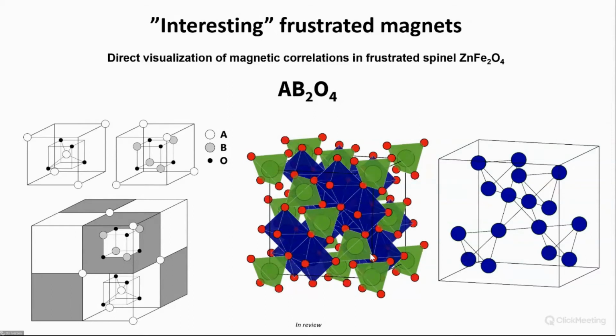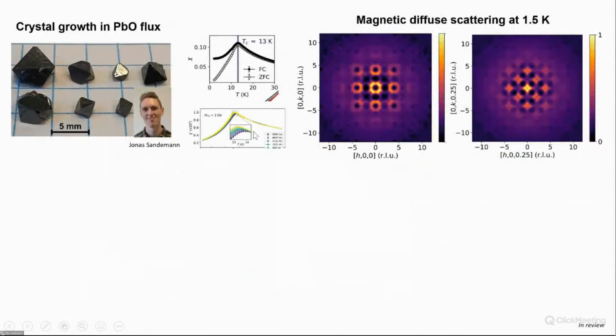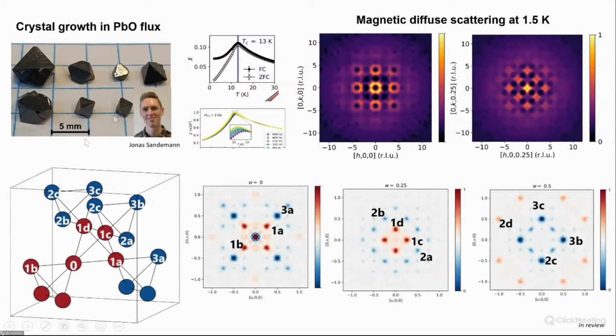So spinel is just another example, again a frustrated magnet. It's a normal spinel, zinc iron oxide, and the iron, the magnetic atoms, sit on this pyrochlore lattice, the B lattice of spinel. And you can do the same. You can spend 2 years like Jonas did here to really grow these jewels of crystals. And then you can measure the diffuse scattering, and you can do the magnetic 3D delta PDF again and look at the magnetic correlations.